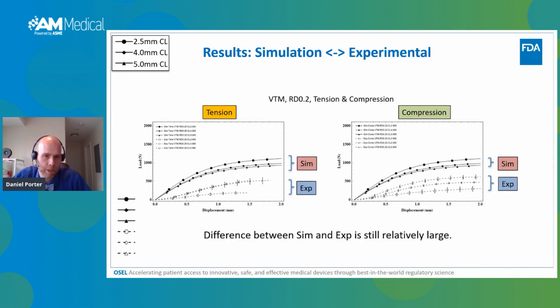Lastly, for the simulation and experimental, we have the Voronoi at a relative density of 0.2, and I'm showing you tension and compression here. What I want to show is that one trend you may get for the compression modality, you might not get for the tension. So you see here in the tension, the two largest diameter struts, given the same relative density, perform within the same bounds. And it was only when we moved to the smaller strut diameter that the stiffness really fell off.